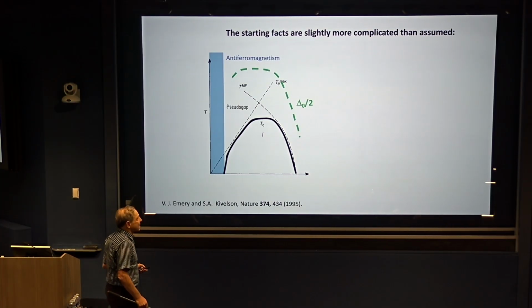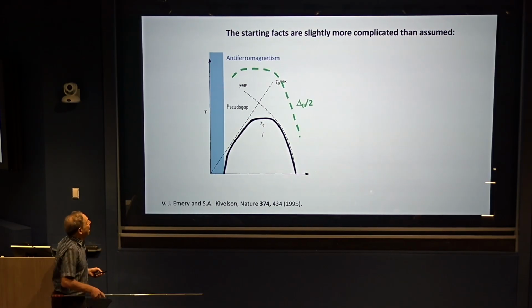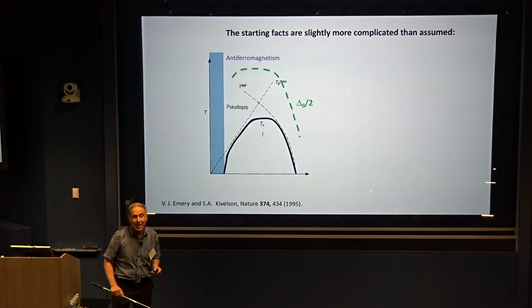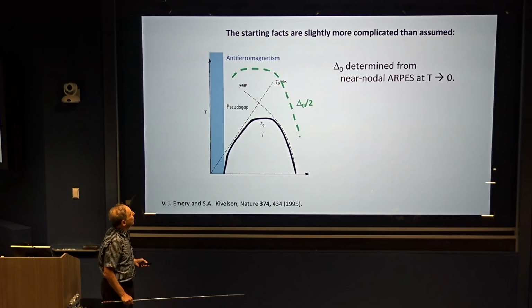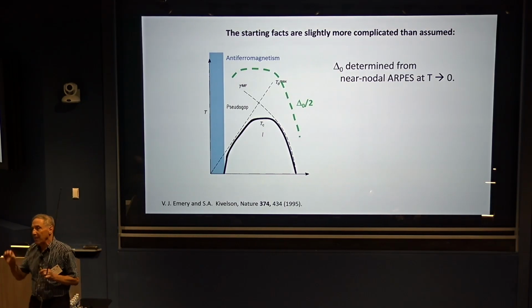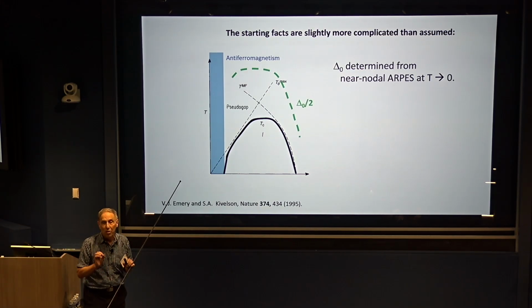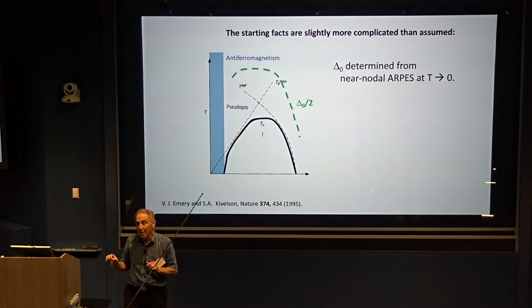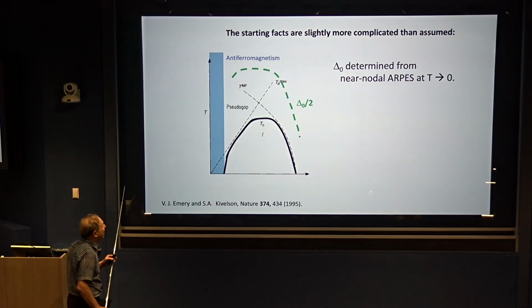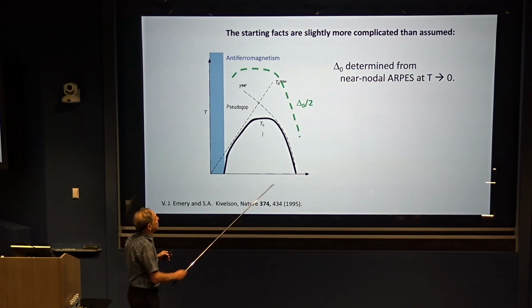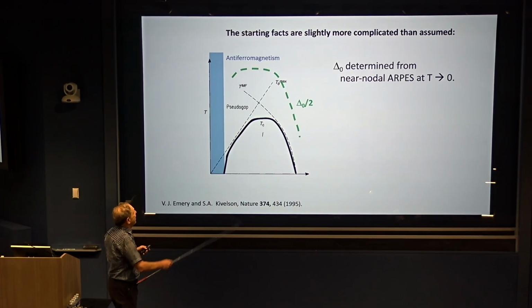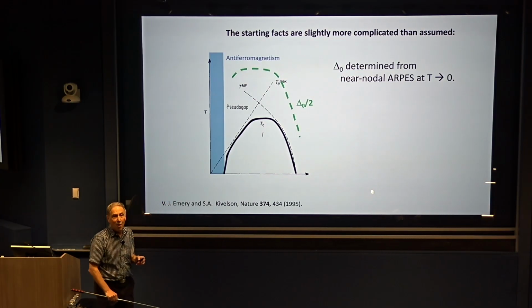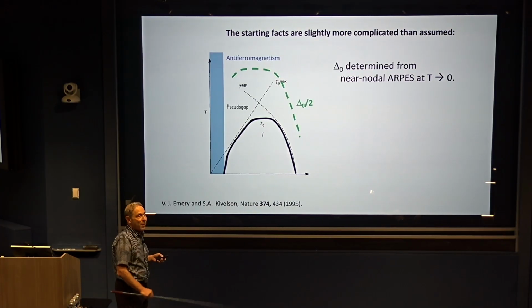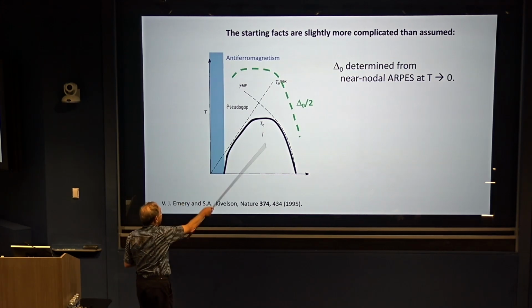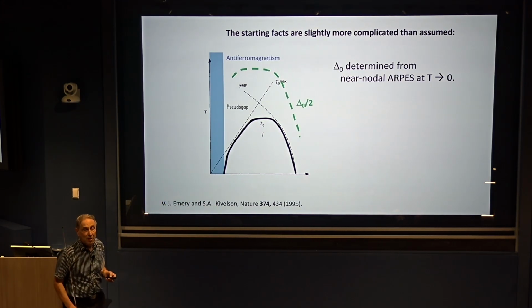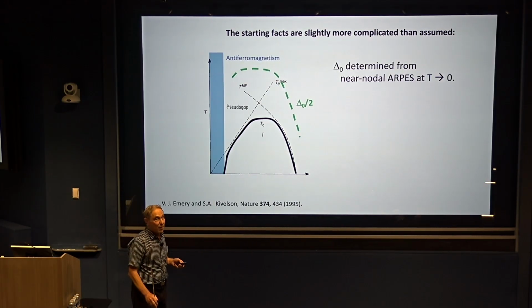A long time has passed since this, and some of it is really clearly correct. You can measure the superconducting gap scale. Gaps don't come with names on them, but if you measure the near nodal gap, you know you're measuring a superconducting gap. This is measured at low temperature, and you can see that the gap is large compared to TC in the underdoped regime and doesn't have the same trends with doping as TC does. That's as expected, and it drops and gets relatively close to the expected magnitude as you go onto the overdoped side. So that turns out to be okay.